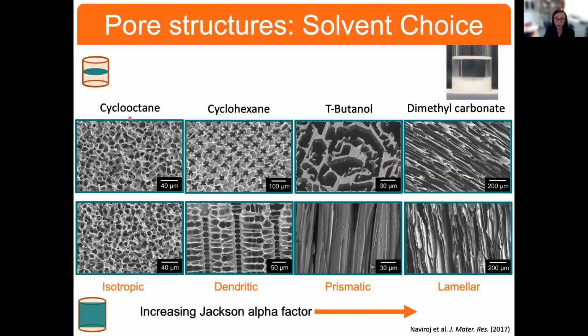Cyclooctane was basically the solvent that should show the least anisotropy, and in fact it does. These particular micrographs are a view looking from the top down. So we've made a cut in the material and we're looking at the solid in this cross-sectional view. And the bottom set of micrographs are the view if we took the cut along the length of the material. With cyclooctane, as you see here, the microstructure looks like a sponge. It doesn't matter which direction you are casting this in. It is completely isotropic.